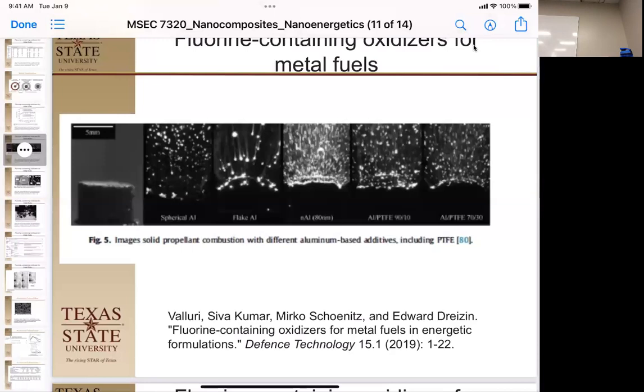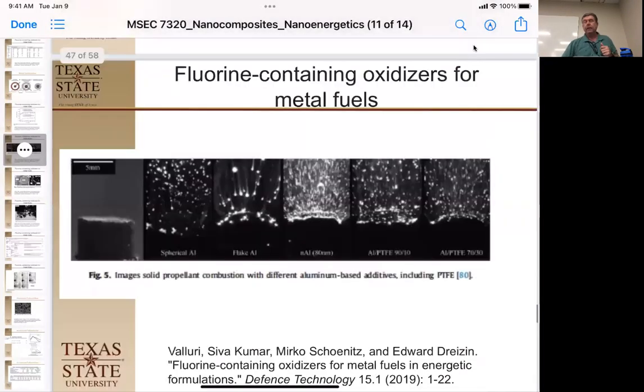In this case here, I think going to a nano aluminum and Teflon would have made it even more exciting. In fact, those are the videos I showed you initially. Those were Teflon and nano aluminum and nano silicon. So which one performed better, the fourth one? So this one probably burned faster, but these two burned hotter. Okay, and these two burned about as hot as your normal spherical aluminum, but notice it's a much more even burn. Can you see that impact?